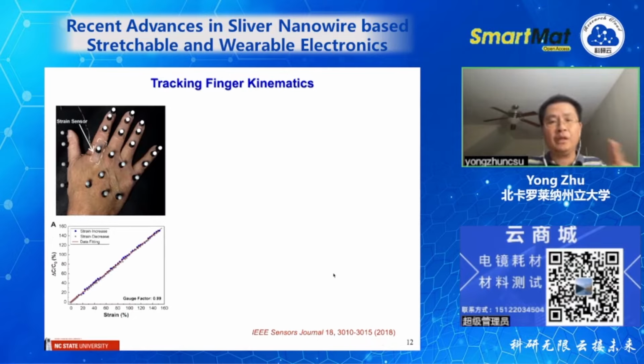I'm going to talk about one particular case. This is the capacitive sensor, and this is the capacitive sensor behavior. The capacitance change is linearly proportional to the strain up to 150%. That is a huge strain. And then it's totally reversible. We did loading and unloading, totally reversible. So that's the major advantage of the capacitive sensor. It has downsides, but these are the major advantages, which is very important for monitoring large deformation.